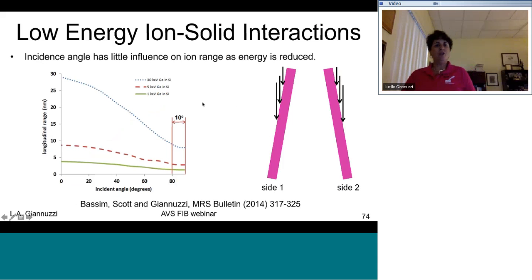So, the other thing, again, I showed you this graph earlier. This actually works to our favor when we do low energy milling. We take a look at our theory and at our ion range as a function of ion energy and incident angle. We see that the ion range varies a bit at 30 kV, but if we go to 5 kV or 1 kV gallium, we see that this is very flat. So the ion range isn't changing all that much as a function of ion energy at these low energies at different incident angles. So what this means is that what's going to work for us at low energy is just the ion energy. And we don't have to worry so much about what angle we hit our sample at, okay? And of course, whatever we do to side 1, we have to do to side 2.